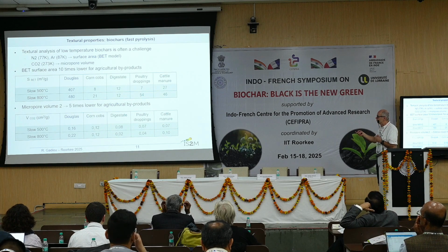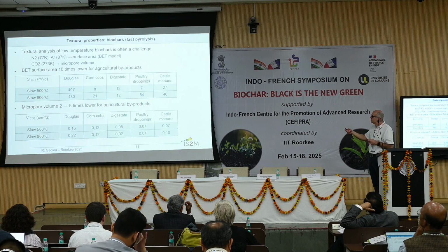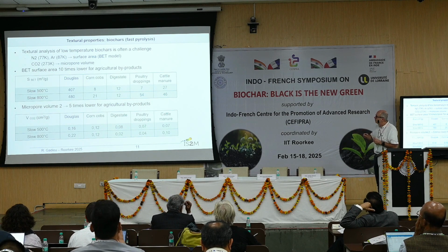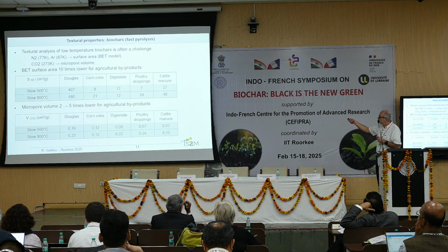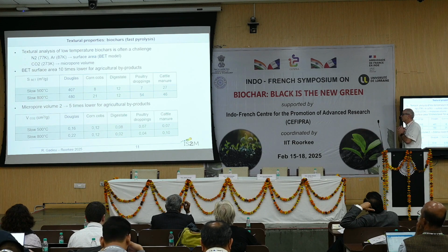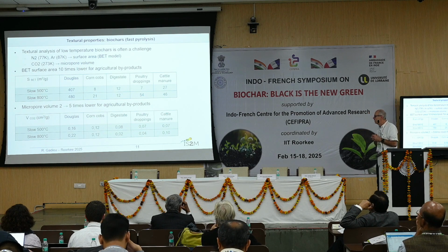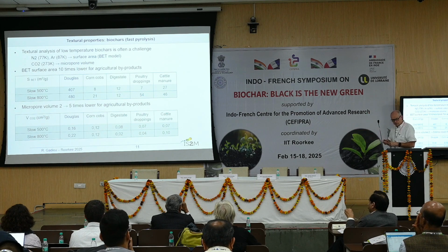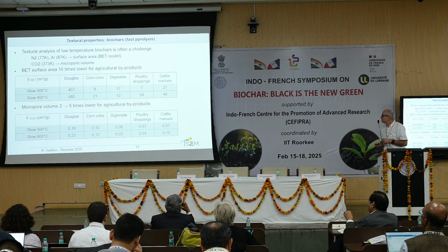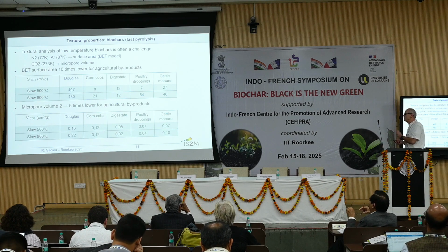An important thing, and we see that for all materials, all biomass with a lot of mineral matter, we have a very low surface area, and also a very low micropore volume, which was measured by CO2. So we have a strong difference between these materials, and this is a limitation for the application.